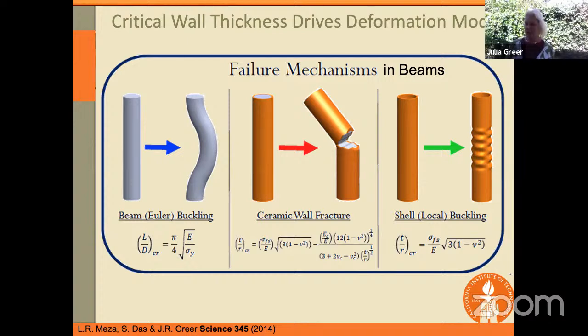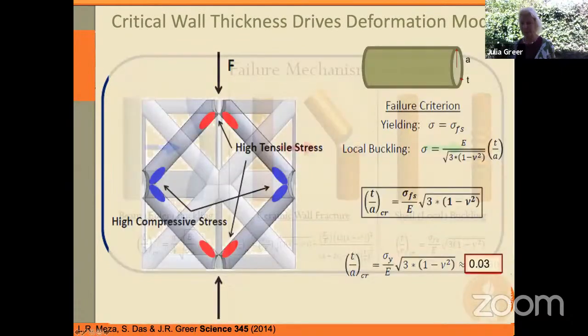Well, the answer actually lies in mechanics. So if you look at failure mechanisms in beams, what we know is that these hollow beams, the situation on the right, experience a local instability called shell buckling. And that is effectively what your soda can would do if you were to step on it. Now, it turns out that there's this critical ratio of wall thickness over the diameter of the beam.